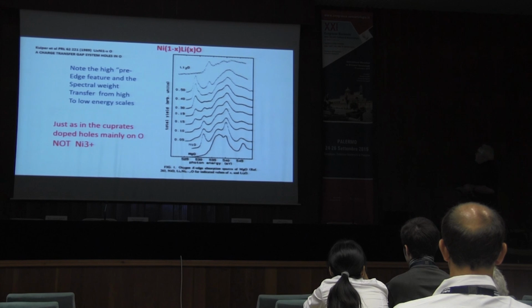And in lithium substituted nickel oxide, you see very clearly, again, this pre-peak in the oxygen 1s X-ray absorption, 1s to 2p transition, which is only allowed if there's 2p holes. And you see this very, very strong pre-peak. And we demonstrated that, in fact, in this material also, the holes do not go on nickel. It is not really nickel 3+. It's actually nickel 2+ and a hole on oxygen. And they are strongly coupled.